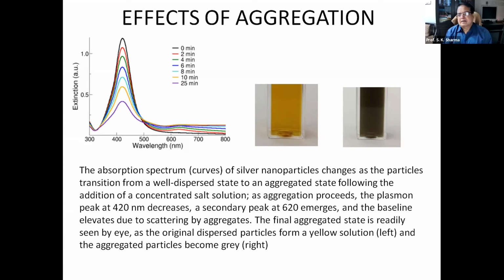So the color of that solution will change from one color to the other depending upon the size. So here you can find that at 0 minute is the topmost curve. As time passes, this curve goes down, but a peak at the bottom also appears. This red one appears, then these blue ones and this magenta curve, they also appear here.